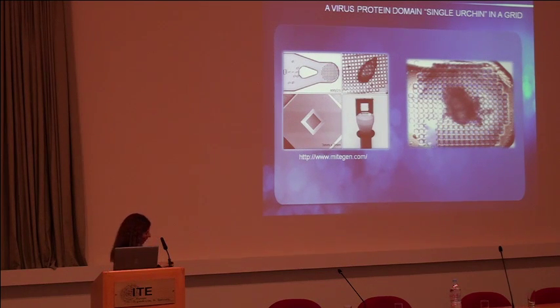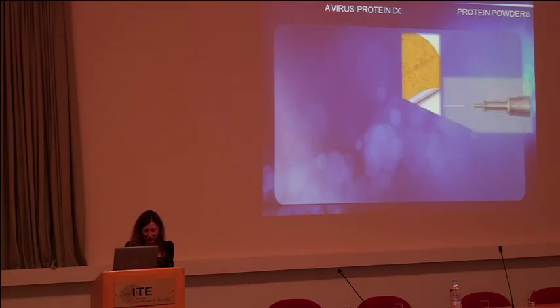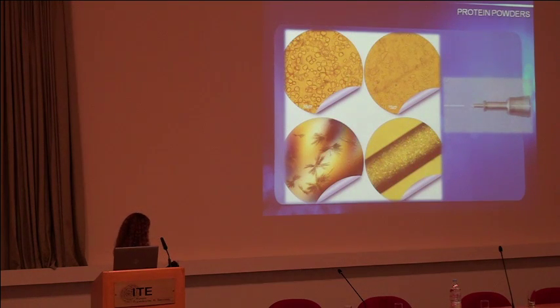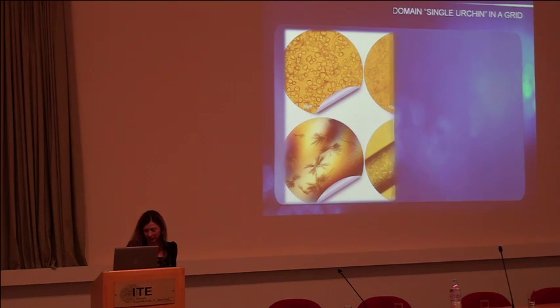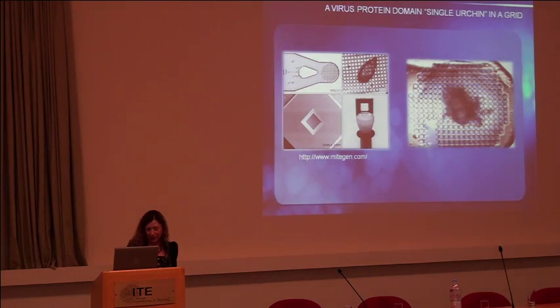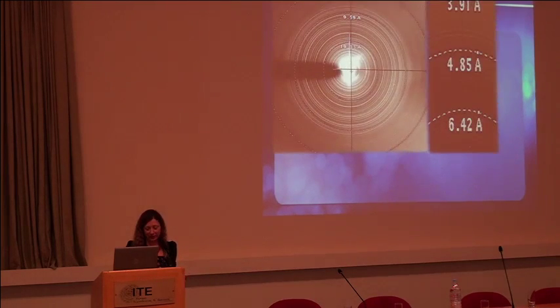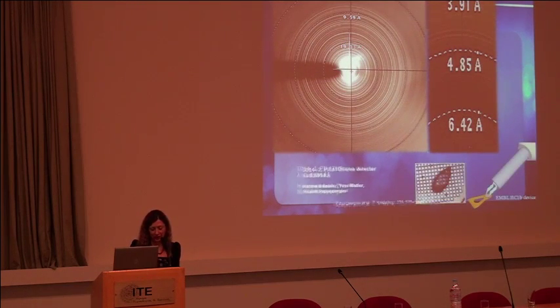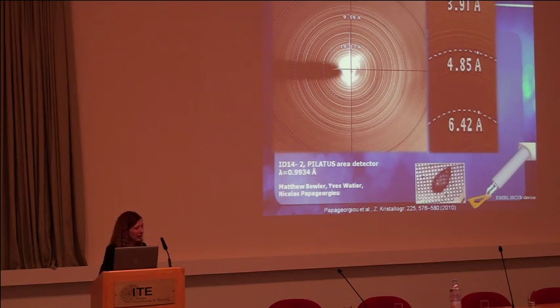You have a loop like these MiTeGen loops, they look like tennis rackets. We scooped a sea urchin that you saw in the previous slide, one of these. Basically, one of these is now our sample. And then we used a single crystal station at the ESRF, ID14, with a Pilatus area detector, and boom, we collected data up to 3.9 angstroms resolution.